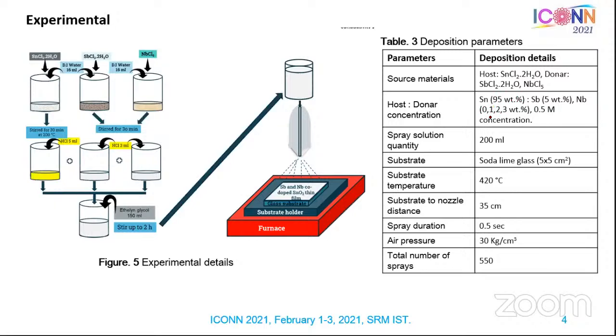So these are the deposition parameters of the spray unit. We used 200 ml of spray solution, and a 5 by 5 centimeter square soda lime glass plate. We coated at 420 degrees centigrade, up to 550 spray coatings.